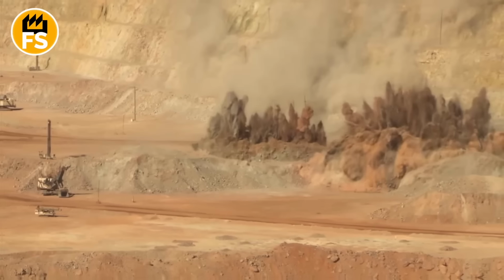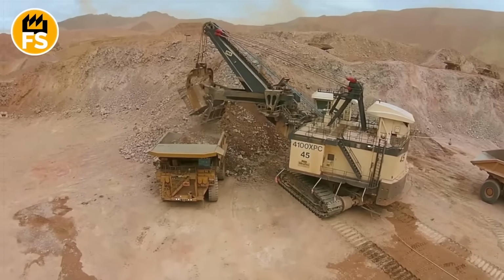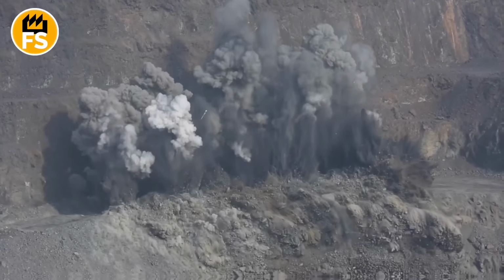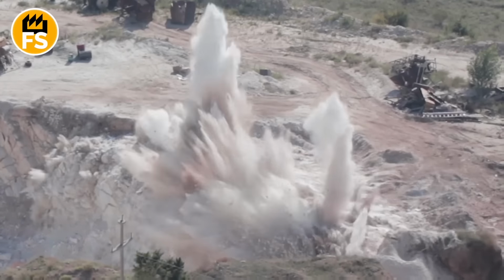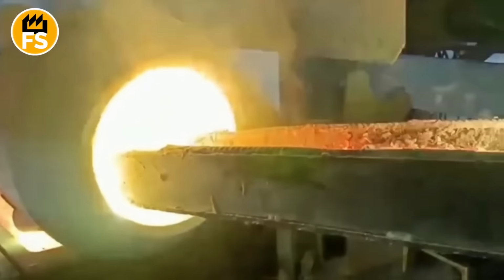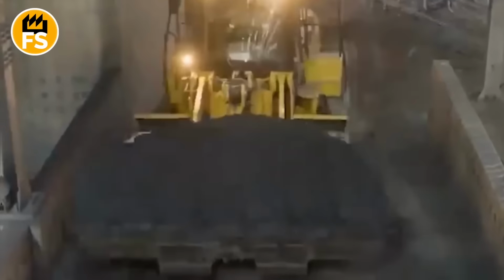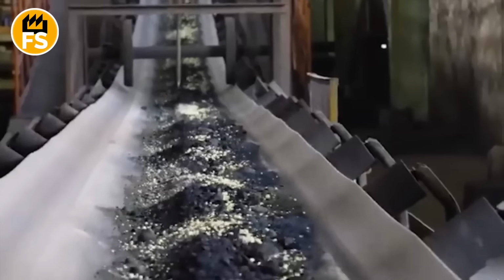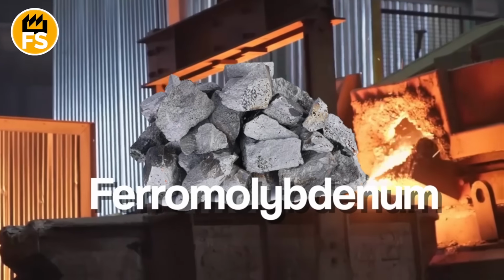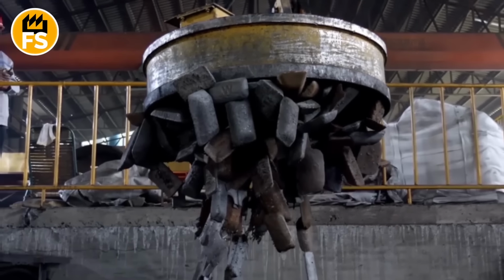Molybdenum is often just a byproduct when mining copper deposits, but its value runs so high that even tiny percentages make extraction profitable. The process of getting metal from rock starts with massive blasting operations in open pits or deep mines. Huge volumes of ore get crushed into fine sand, which then heads to flotation plants. There, in a water environment with special reagents added, molybdenite particles attach to air bubbles and rise to the surface, forming a concentrate. This gray mass later goes through a roasting stage at high temperatures, where the sulfur burns off, leaving molybdenum oxide. This powder becomes the foundation for producing ferromolybdenum, an iron alloy that's the main component in the metallurgical industry.